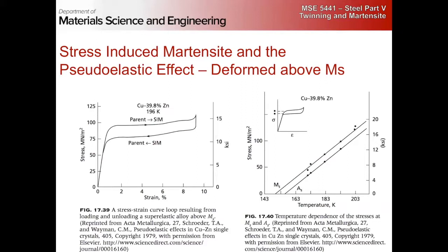Right? So you notice that once the transformation really starts, your stress doesn't increase. Once you're at the end of your transformation, your stress starts to go up. If you continued to pull this, it would deform plastically and break very quickly because the martensite doesn't have a lot of ductility, right? If you pulled it any more than this, just so it started to yield, you would not get full recovery, right? So there's a limit to the pseudoelastic effect. Once everything's completely martensitic, bad things happen, right?